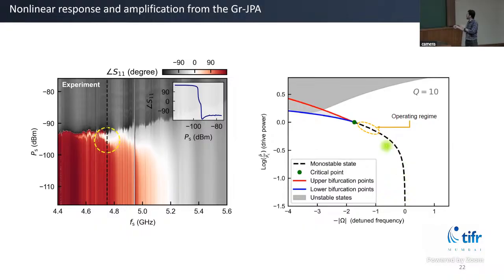Now when you increase the power, the frequency starts to bend and eventually reaches a critical point beyond which it becomes unstable, as I said in the earlier slides. The system has multiple solutions mathematically. And in RF terms, the device just becomes lossy, the resonance goes away. The correct biasing point would be just before this critical point. So you sample the maximal nonlinearity, but you are not hitting the critical point. This is our region of interest, where we explore most of the interesting things, which is this yellow circle marked here.